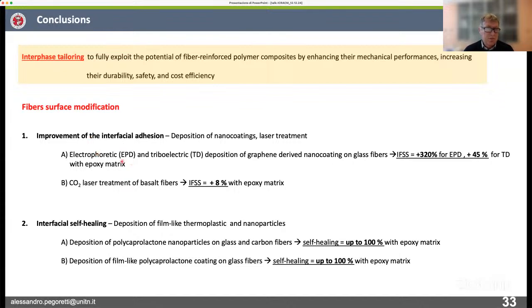One was to deposit by electrophoretic deposition or triboelectrification a layer of graphene, and then basically we use graphene oxide and reduced graphene oxide for this, reaching very important, very interesting results in terms of improvement in the adhesion. In the second case, we use a laser treatment. The results were less intense in terms of interfacial shear strength improvement, but the technique is very fast, very quick. It does not require any chemical. So maybe we will continue in this analysis in order to see if some better result can be obtained also by using this laser treatment.